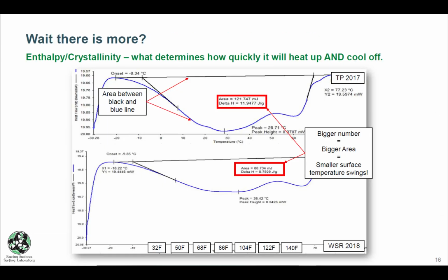So I want to talk about one more thing, and that's enthalpy and crystallinity. And this is like when I talked about steel versus aluminum. This is really one of those bigger differences: how quickly will the wax heat up and cool off? And we can actually measure that relative to one another. If we have this crystallinity, that means we have these semi-crystalline regions in the wax. Without getting into too much detail, what it means is that it takes more energy, more heat to heat the wax up, or it can take less energy.